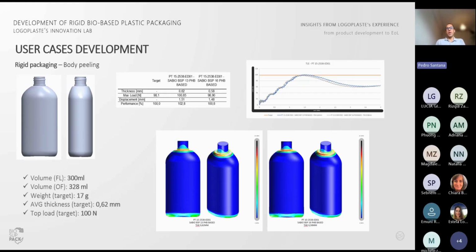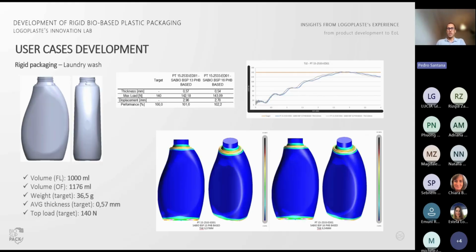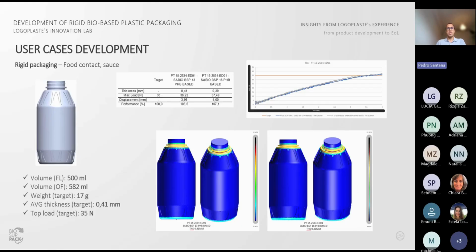In the case of the body peeling packaging, a slightly higher average wall thickness was obtained, even though the package was quite similar to the previous one. Nevertheless, the results remain within the acceptable limits for both the technology used and the specific type of packaging in question. The same for home care packaging. And here you can see that due to its larger dimensions, a higher top load specification was expected. However, thanks to its favorable geometry, it was possible to achieve an average wall thickness similar to that of the previous case study, while still meeting all the defined technical requirements.